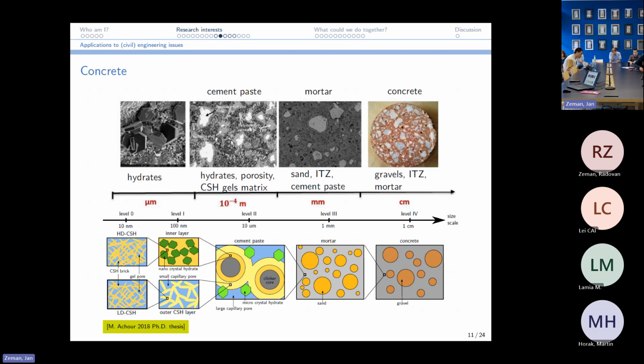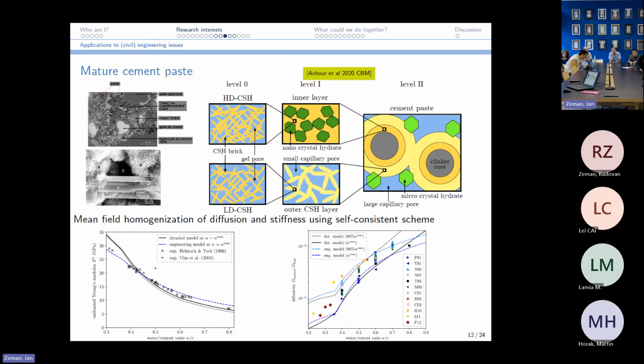Okay. So usually to describe this, people use a cascade of multiscale techniques, with many scales involved, and you have many scale transitions. So we did that, having some project related to the resistance of concrete to chloride penetration to prevent the corrosion of steel rebars. There are many things in the literature that do that already, but they either do it for diffusion or they do it for elastic or mechanical properties. But I wanted to have a model that can do both at the same time. And for that you need a microstructure description that is accurate enough.